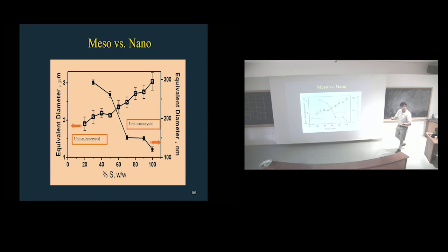When we're looking at the microscope at micron-sized things, unit microcrystals, believe it or not, when you increase the supersaturation, like I showed you before, we get a reduction in crystal size, because that's what should happen with nucleation. Increase the supersaturation, it goes faster, and you get smaller crystals for the same amount of solids. But we take the picture under the polarized light microscope, and this thing is going the other way. It's like, what the hell? This is governed by the laws of chemistry. This is like drunk, it's going the other way. How come I get bigger microcrystals when I'm getting smaller nanocrystals?